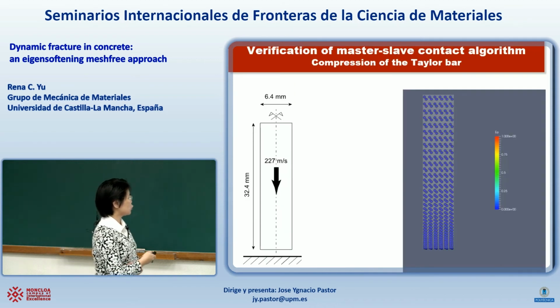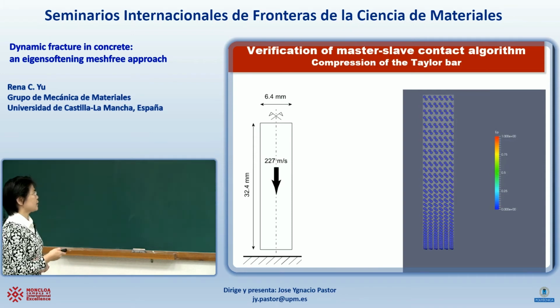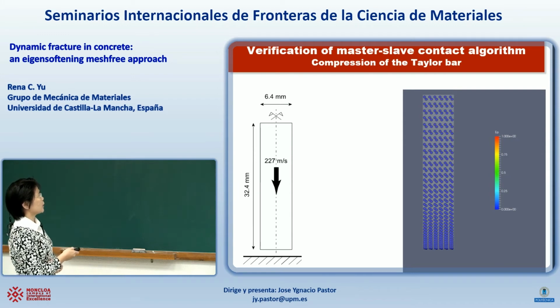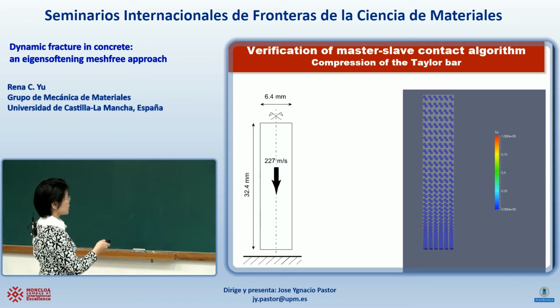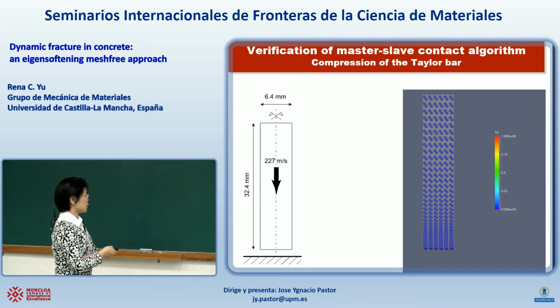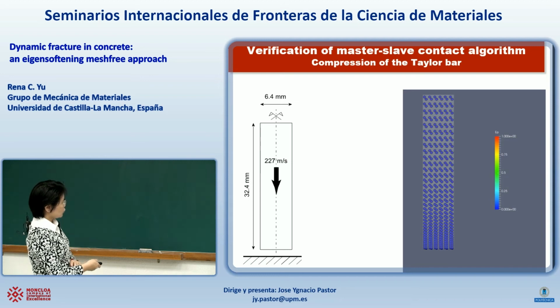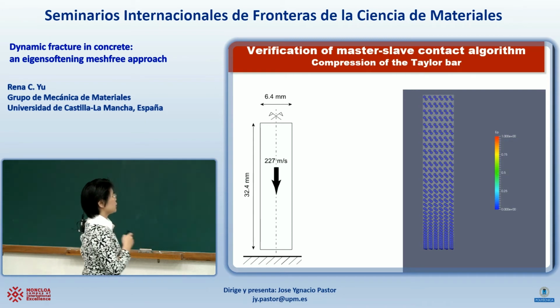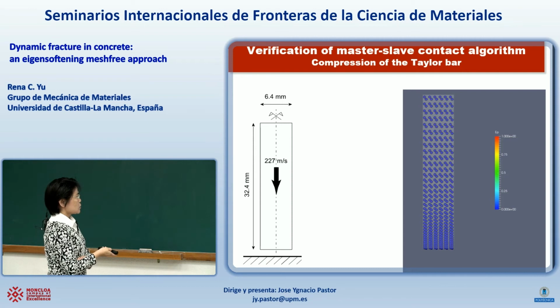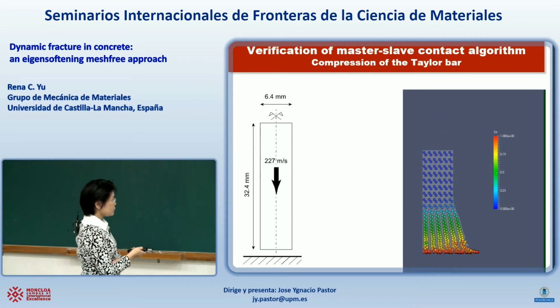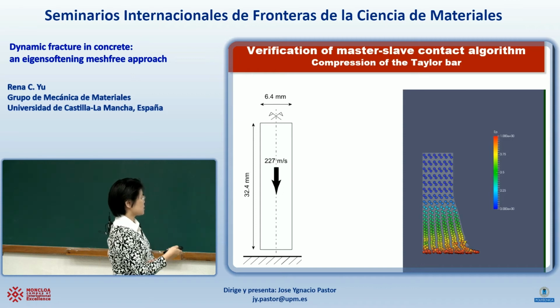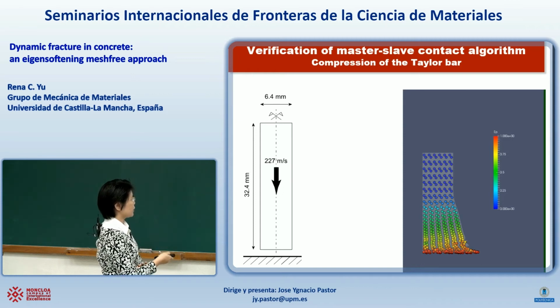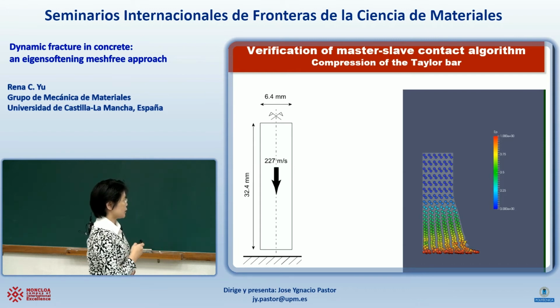This is, I just saw a video showing how we verified the contact algorithm they developed for a benchmark test, the compression of the Taylor bar. The material is copper. This is a diameter of 6.4 millimeters. This is the length, 32.4. It goes down towards the rigid floor with a velocity of 227 meters per second. So we model that. We see how this Taylor bar is being compressed, especially here where there is great deformation. The color code is for plastic deformation.